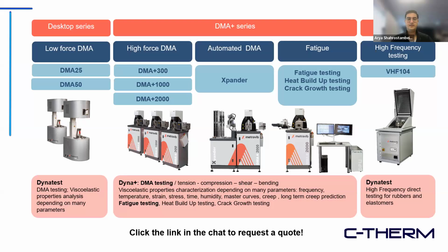So the desktop series can go up to 200 hertz for frequency, but Plus series DMA can go up to 1,000 hertz and up to 2,000 Newton force peak to peak, with added capability, for example, fatigue testing, heat build-up test, and an automated solution provided by Metravib. Basically, you can run your test 24/7 without interruption using a robotic arm. And on the right-hand side, you can see a high-frequency analyzer, VHF104, that can measure the viscoelastic properties of material for higher frequencies, ranging from 100 hertz to 10,000 hertz experimentally, without any calculations or any master curve building or extrapolation.